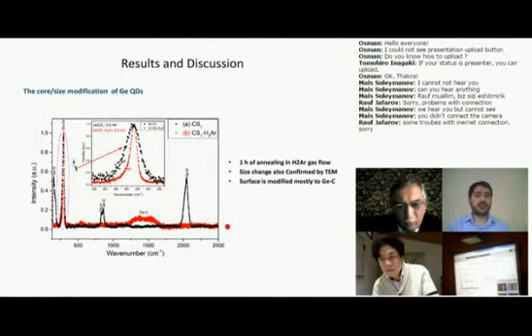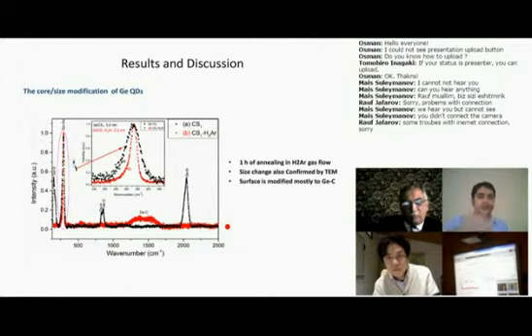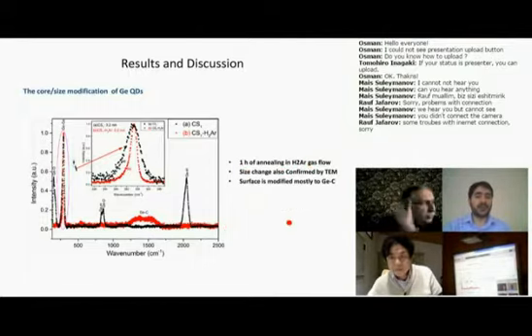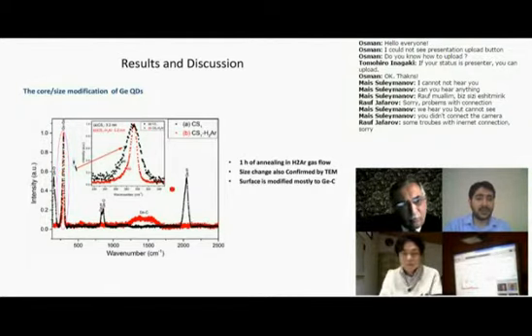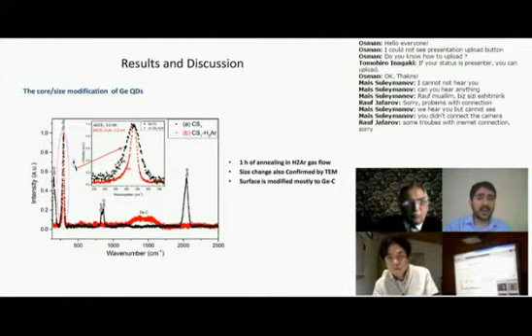Okay, after that, I also showed that I'm able to change the particle size and also the surface of the particle by annealing the particles. It's after 1 hour annealing in hydrogen-argon gas flow. The black one is the prepared sample.